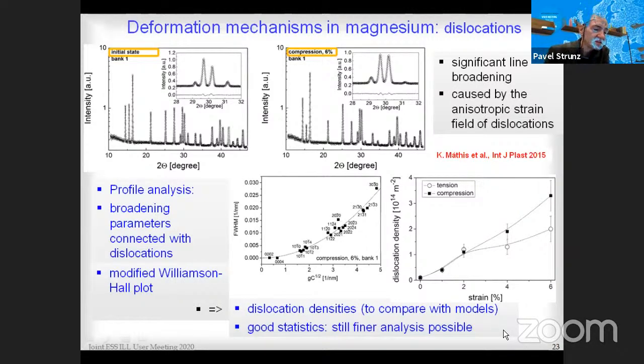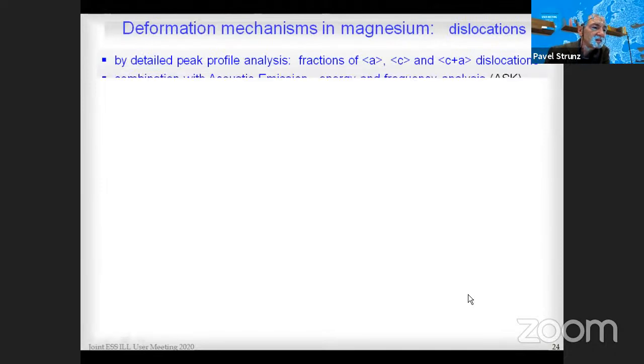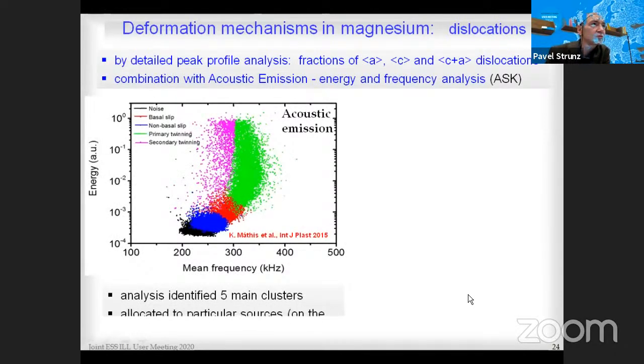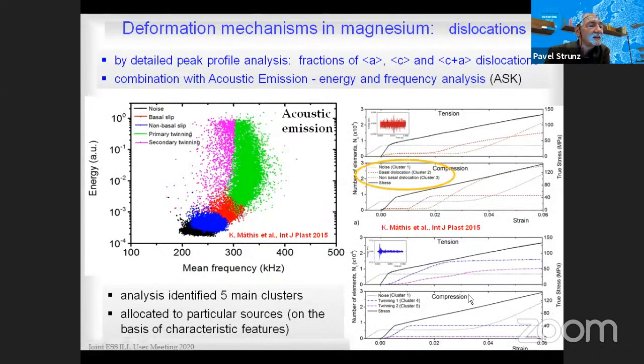Having very good statistics of the data, we can do still finer analysis. Particularly, we can determine the fraction of basal and non-basal dislocations. And this can be combined with advantage with acoustic emission results, particularly with energy and frequency analysis, which is shown here. In this way, you can decouple different contributions to the deformation. And for example, recognize that in the compression, first there are coming basal dislocations and then slip from non-basal dislocations takes place.